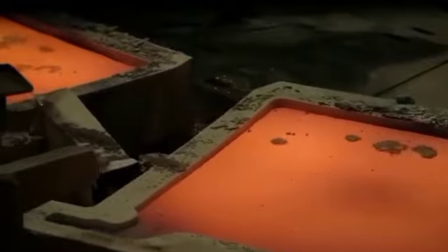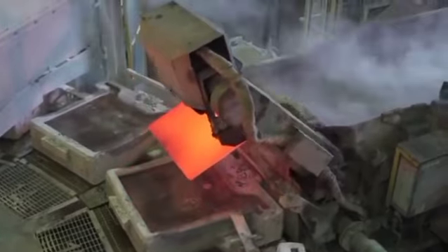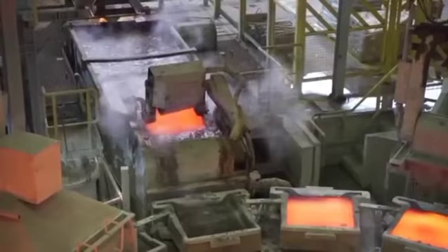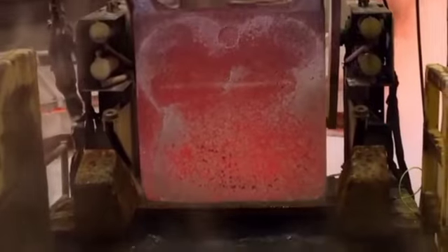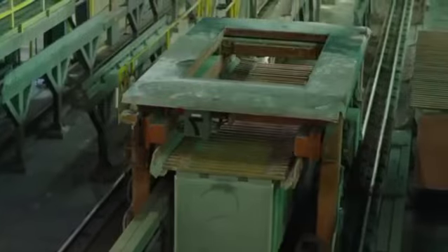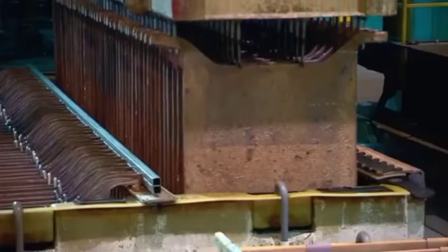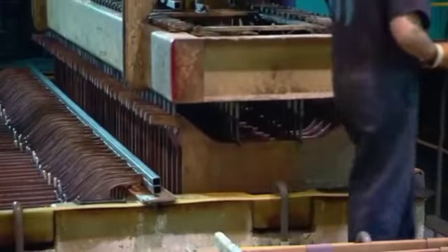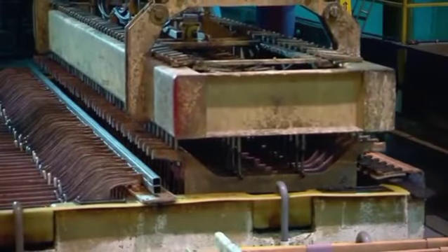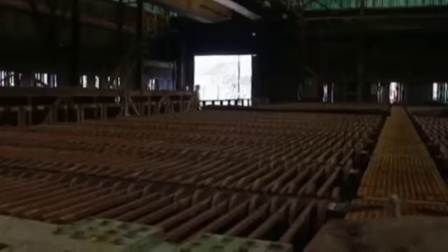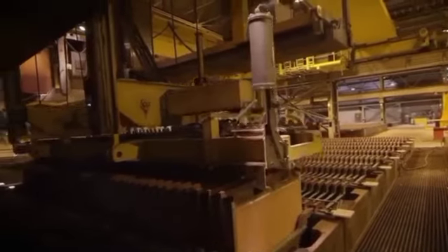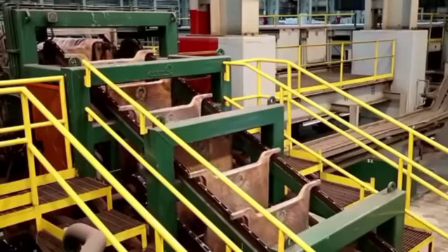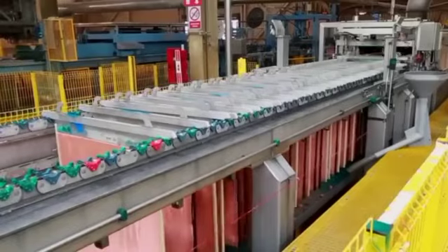At extreme temperatures, the mixture turns into a molten liquid. The slag, composed of iron and other minerals, floats, while the copper sinks. At this point, the purity reaches 60%. It then passes to a second furnace, where the copper content rises to 98%. The molten residue is poured into a pile, a stream of glowing slag flowing like molten lava. As it cools, it solidifies and becomes part of the landscape.